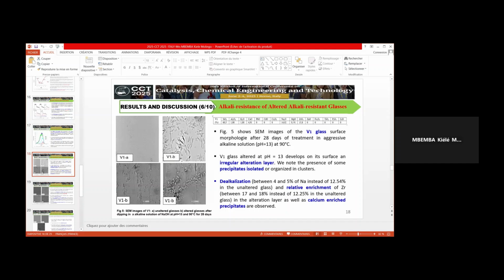So concerning alteration, we can see in figure 5 the image of the V1 glass surface morphology after 28 days of treatment in aggressive alkaline solution at pH 13 at 80 degrees Celsius. We can see that V1 developed on its surface an irregular alteration layer. We note the presence of some precipitate. We also note dealkalinization